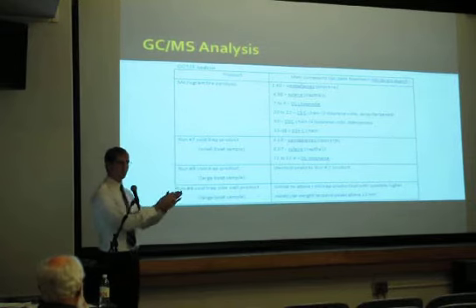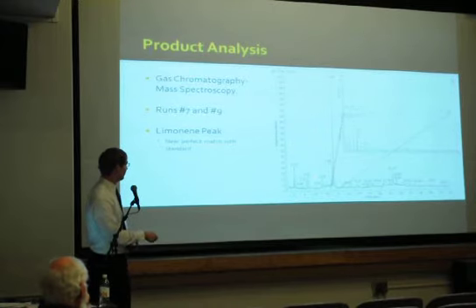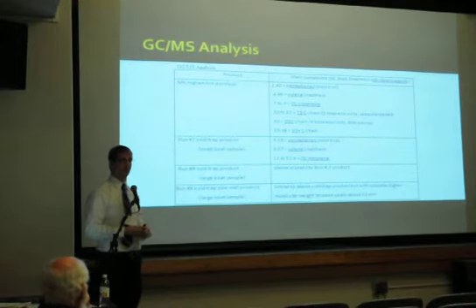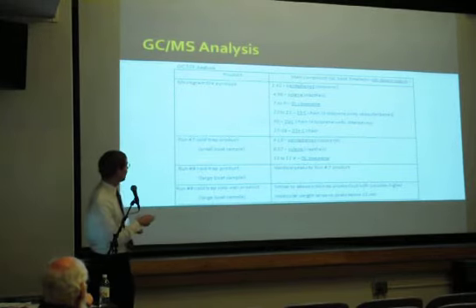So we saw different various groups if you come back here. Since this is run number 7, we saw this group here, and then we see this larger group here. In our full tire analysis, we saw several other groups further on that we expect to be larger terpene samples. So 3 isoprene units and 4 isoprene units, which corresponds with 15 carbons and 20 carbons.